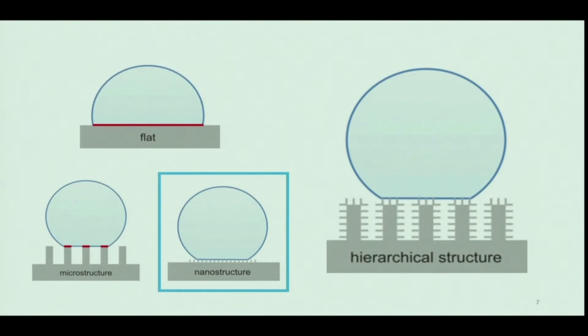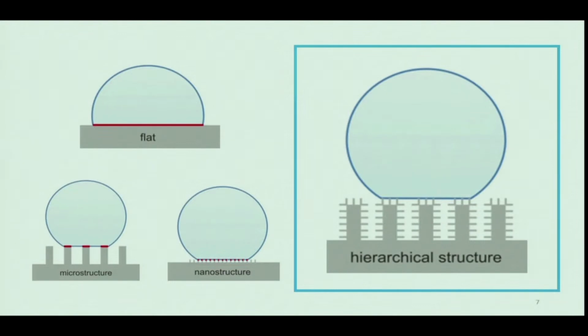In the case of only nanostructures, the contact area is even smaller than only microstructures, improving the ability of water to be removed from the material. But it's not the ideal scenario yet. For the hierarchical structures, the contact area is the lowest possible. And as a consequence, the water droplets easily roll off the surface, characterizing a superhydrophobic material.